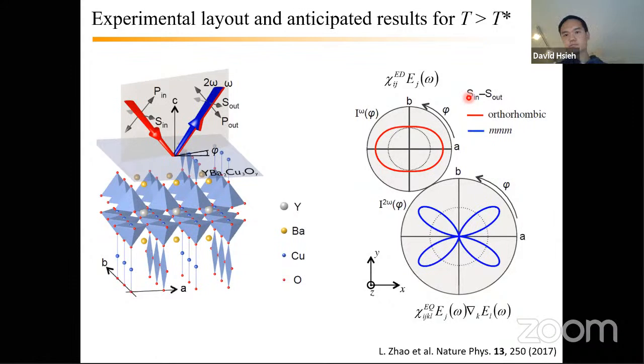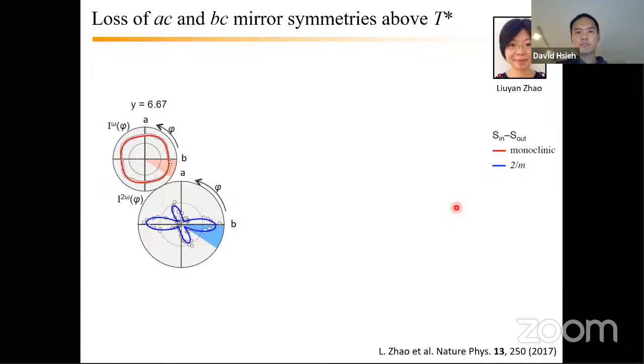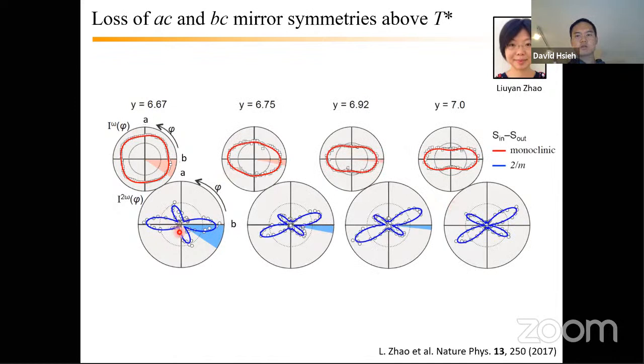In the linear channel, you should see this oval structure, okay, with high symmetry directions along the a and b axes of your orthorhombic cell. And then in the second harmonic channel, your pattern should look something like this, again reflective of this mmm symmetry. So in fact, this is not what we see, okay? So here is data above T star at various doping levels, and you can see that there's already this departure from this mmm type structure in both the linear and the SHG channels.